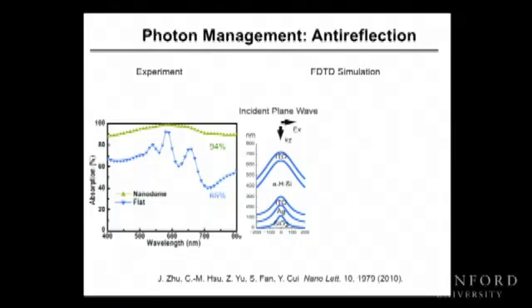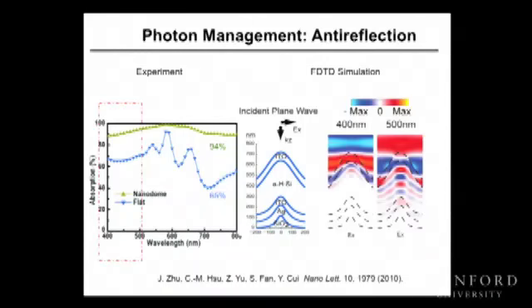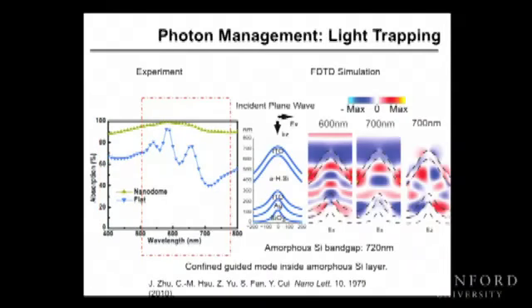This is also the nature of this consortium. We want to encourage collaboration between scientists of different expertise. In this case, it is a collaboration between my group and Professor Shanhui Fan right here, using FDTD to demonstrate that for the shorter wavelength, the absorption difference is really due to the anti-reflection effect. For the nanodome, you can have light coming in, looking at this intensity distribution, 400 nanometer light coming in and getting absorbed completely. But for the longer wavelength range, looking at 700 nanometer, we figured out light coming in travels horizontally and gets trapped inside this amorphous silicon, resulting in this high absorption inside amorphous silicon.